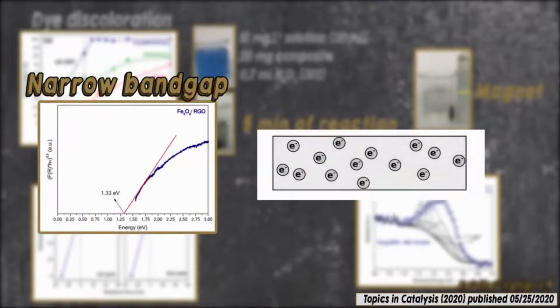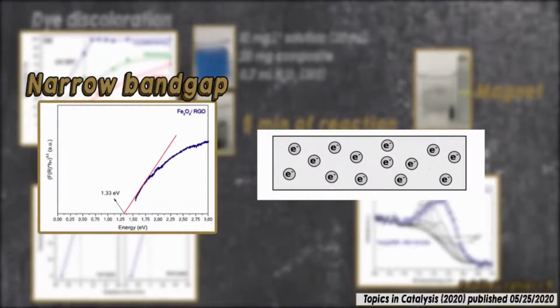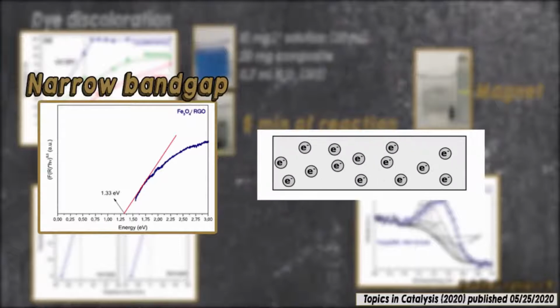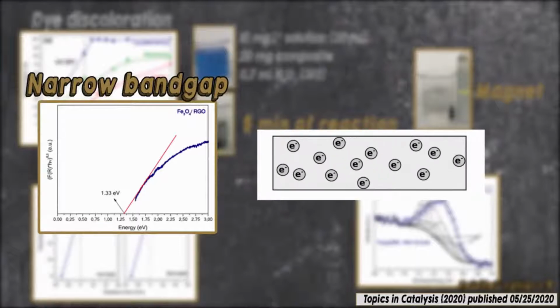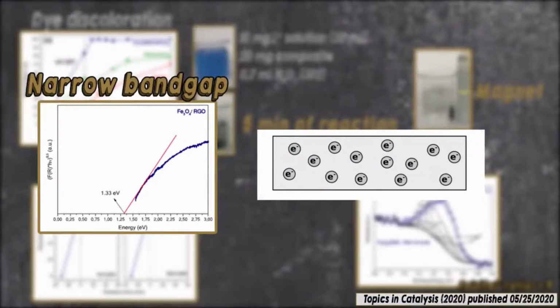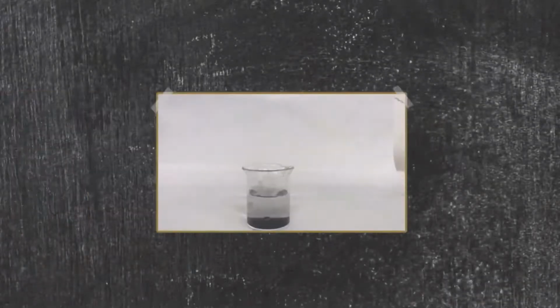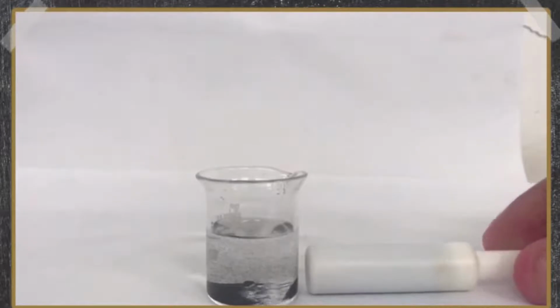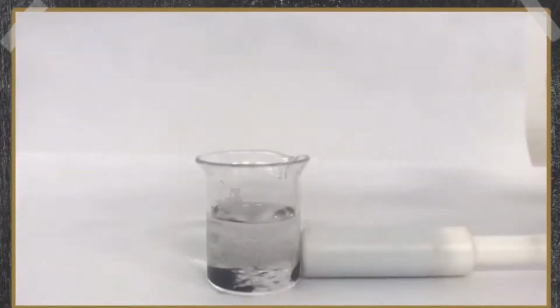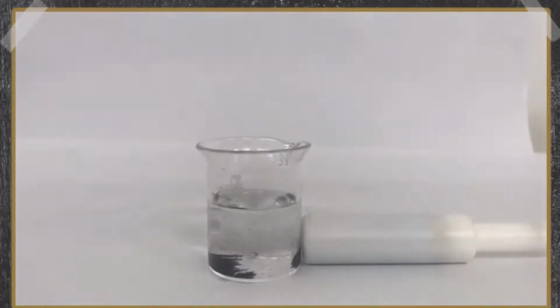The excellent performance of this composite can be attributed to the composite's narrow band gap. A narrow band gap means that we have an excellent electron mobility, which is the key factor for a good photocatalyst. Here is a short video showing that with a simple magnetic bar, we can easily separate our composite from the medium.